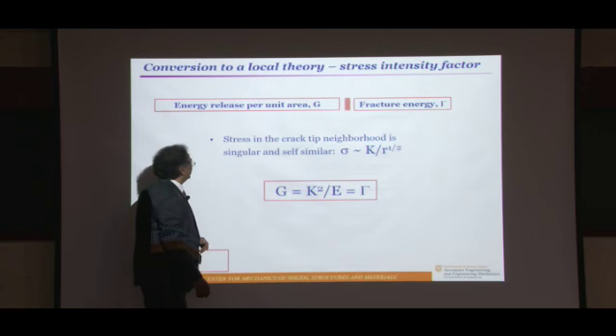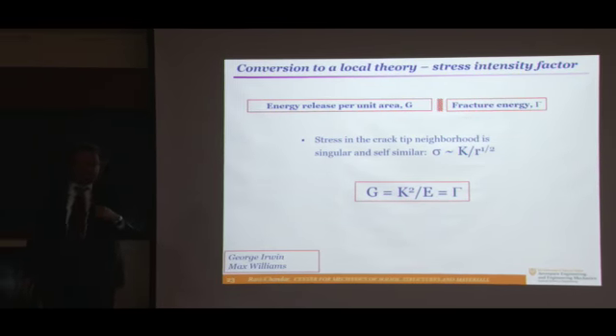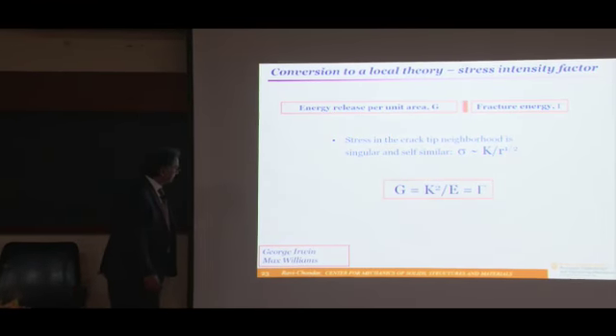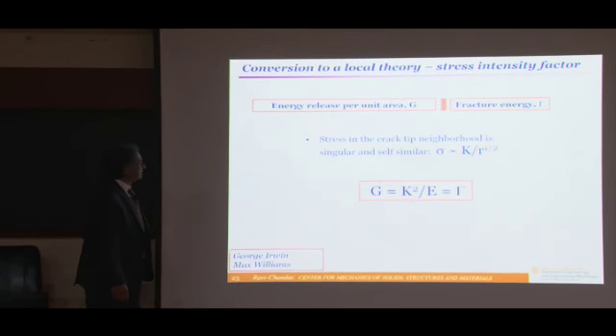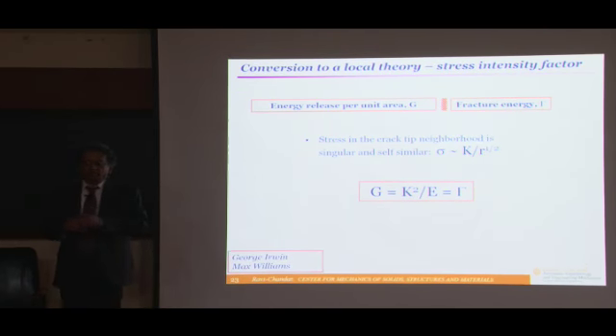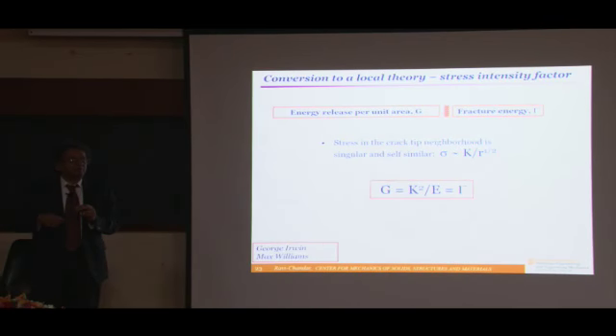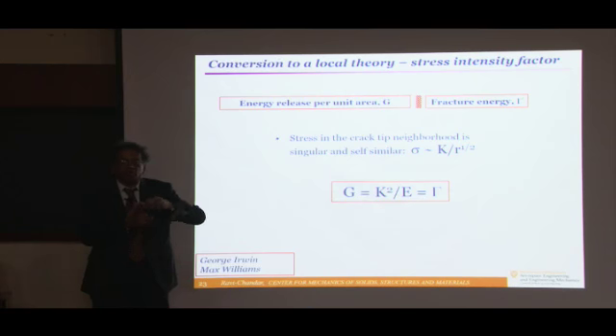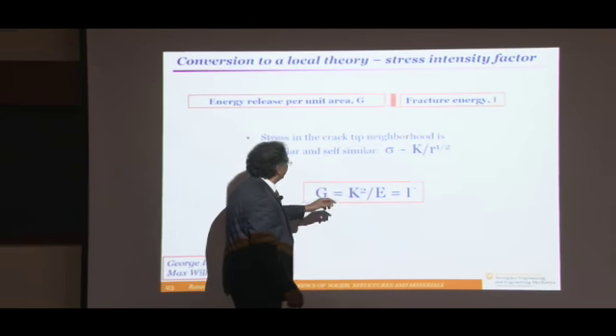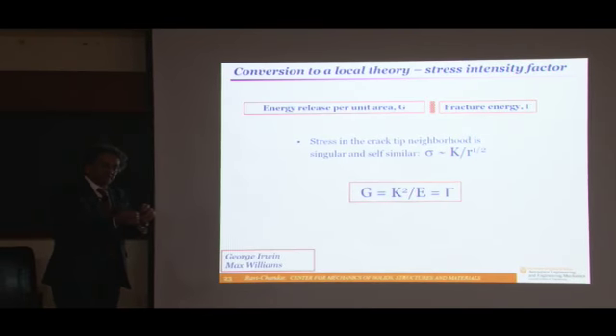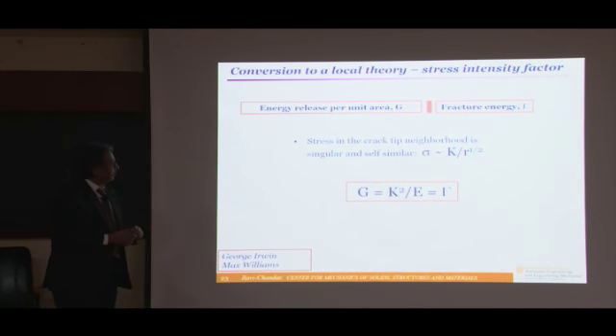There's been a very large kind of cottage industry calculating this quantity, the stress intensity factor, for numerous geometrical arrangements and cracks. One example that I've shown here is if you had a plate of some width W and you had a crack of length A loaded with a load P. This is the load P at which failure will occur for this particular geometry. Places like Boeing and other companies have created huge charts of this kind of residual strength diagram that take into account not just the strength of the object, but also the presence of a crack.